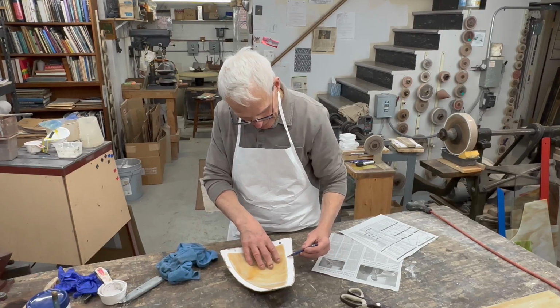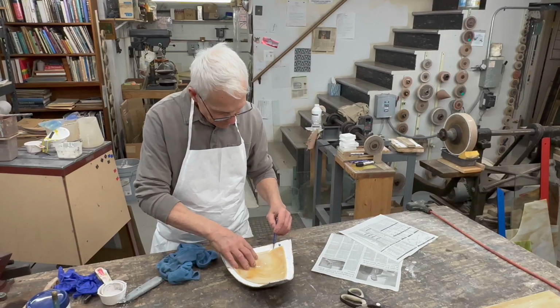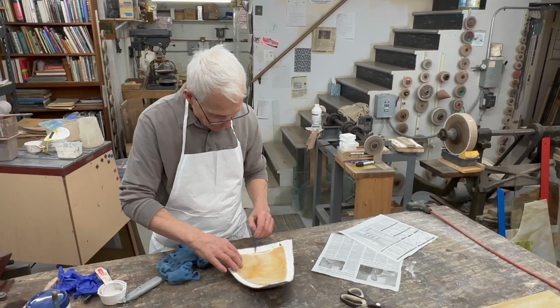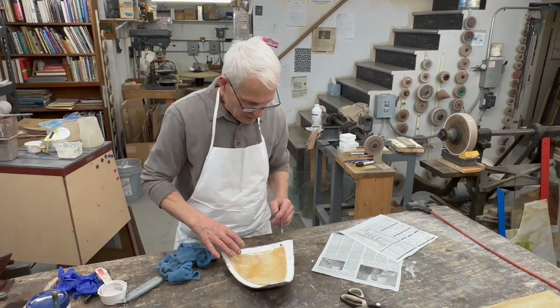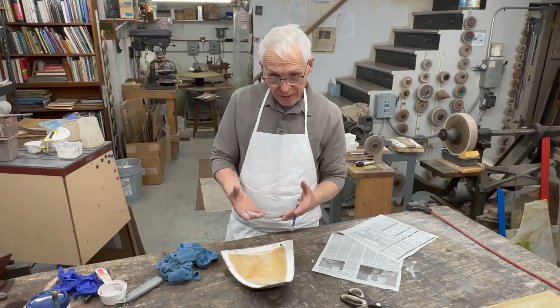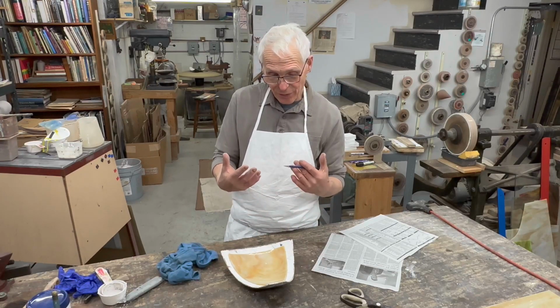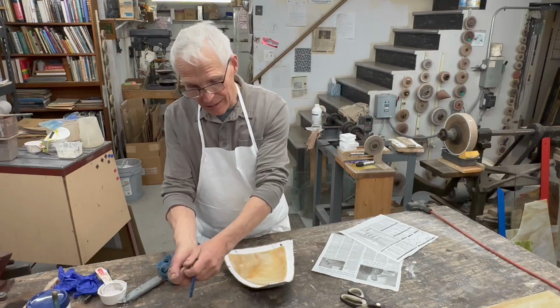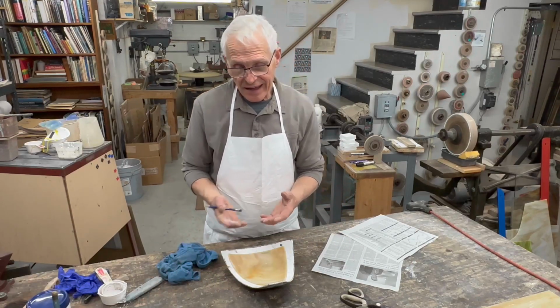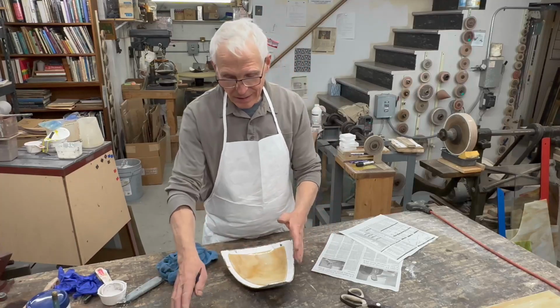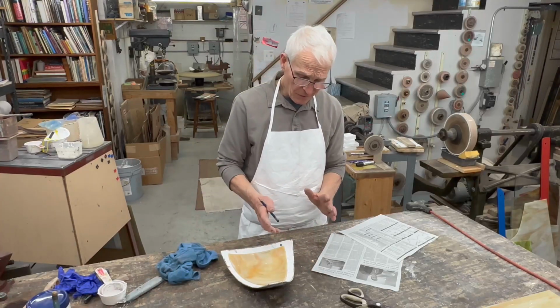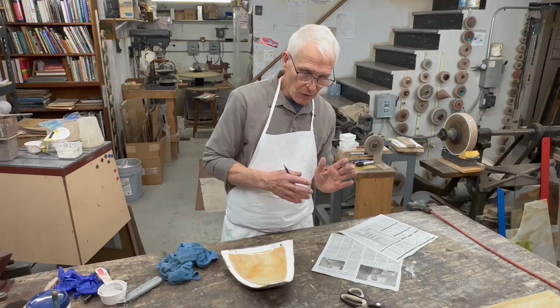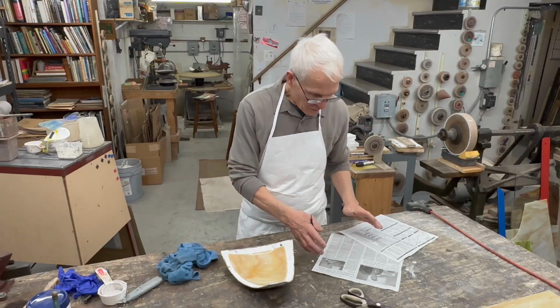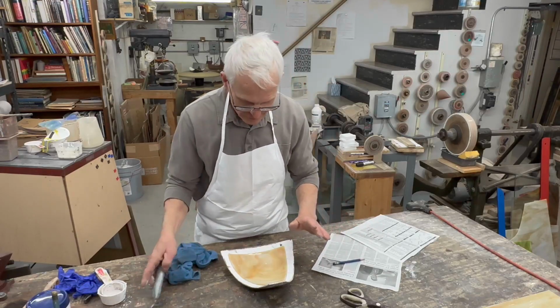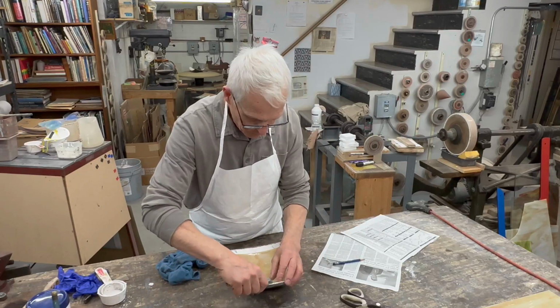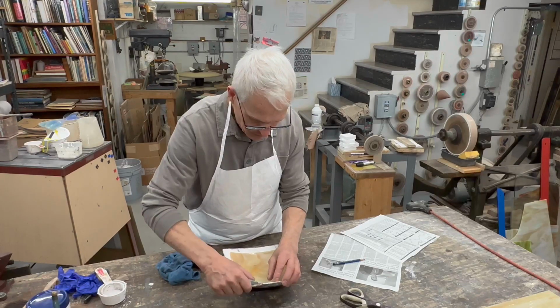I'll be bending this panel most likely in the gas kiln, and at that point I have the ability to take it and pull it out of the kiln, not pull it out in my bare hands, but take the shelf that's on casters, pull it out, make the adjustment if it didn't fall 100% correctly, and then roll it back in and heat it up again. So first things first, we've got to get our blank.